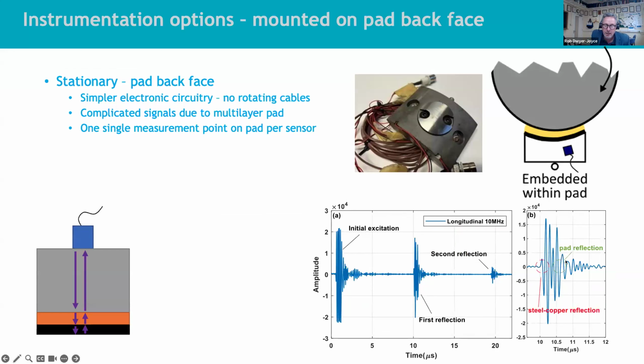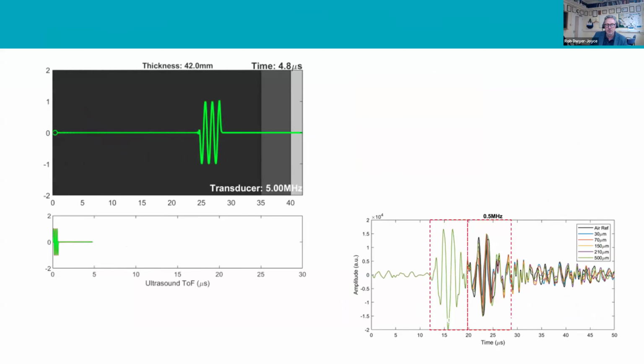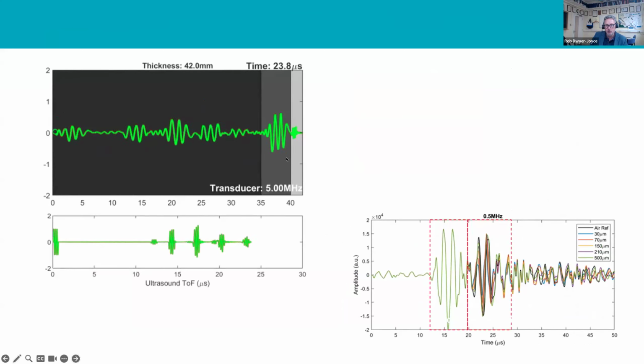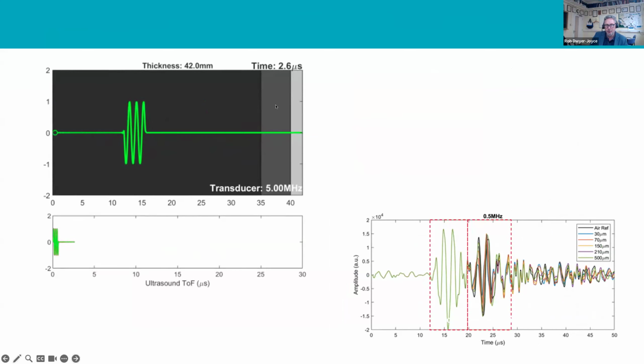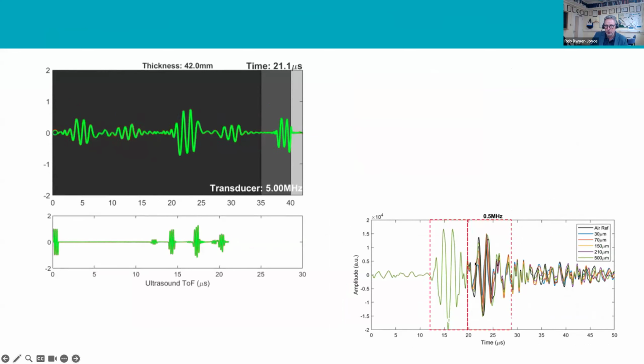And it becomes a little bit tricky to separate out the reflection caused by just the oil film, that's the green one, from reflections from other things like the steel copper reflection here. So whether this is going to work will depend very much on the construction of the pad. If these layers are thin, it's going to be successful. If they're thick, it's probably not. Here's a sort of a simulation of the process, and you can see why. You can see why as you get all these multiple reflections bouncing back from the interlayer, from the polymer layer, they all superimpose and you get a complicated signal.